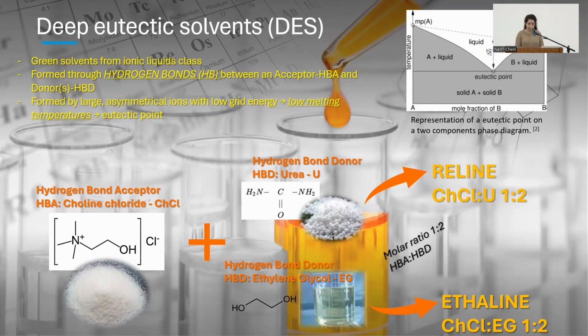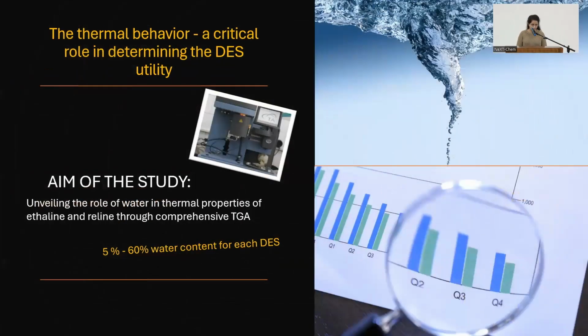The first one, the Reline, is composed of choline chloride as the hydrogen bond acceptor and urea as the hydrogen bond donor. The second solvent used the same hydrogen bond acceptor, choline chloride, and the donor this time was ethylene glycol. Both solvents had the molar ratio 1 to 2, hydrogen bond acceptor to hydrogen bond donor.